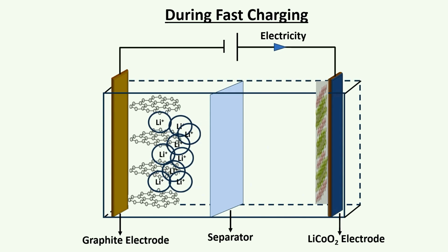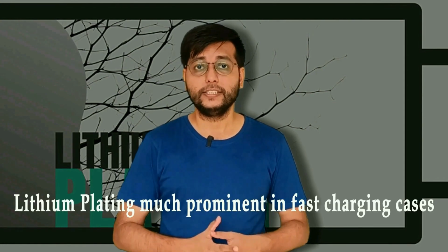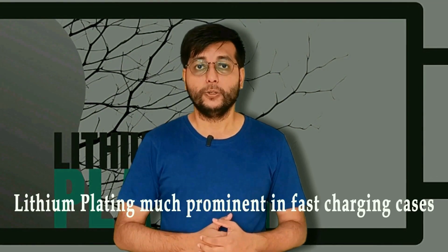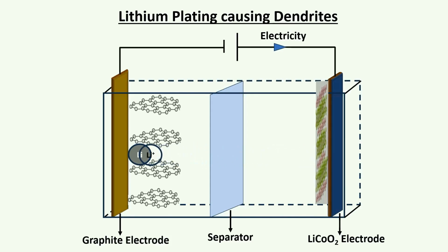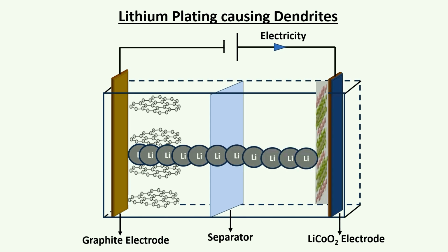During fast charging, the high current leads to accumulation of the lithium ions on the graphite anode, and this causes the drop in the electrochemical potential of the graphite anode, resulting in the deposition of the metallic lithium on the graphite anode. Although charging at low temperature causes lithium plating due to the low diffusion rate of the lithium ions, the serious case of lithium plating occurs when charging is faster. This lithium plating can cause the formation of dendrites, which elongate from the anode, can even pierce through the separator, reach the cathode, and finally